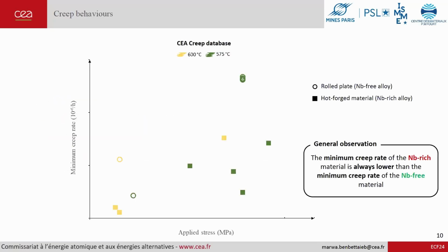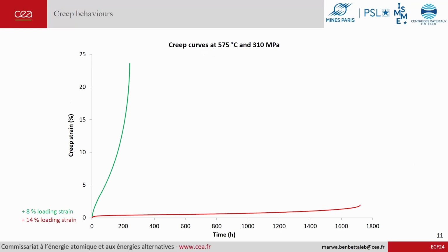Moving on to the creep behaviors. So according to the CEA creep database, presented in this diagram by the minimum creep rate versus the applied stress at different temperatures, at the same conditions, we can see that the minimum creep rate is always lower for the niobium-rich alloy compared to the niobium-free one. For the rest of the presentation, I'd be interested in the creep tests carried out at 575 degrees C and 310 MPa.